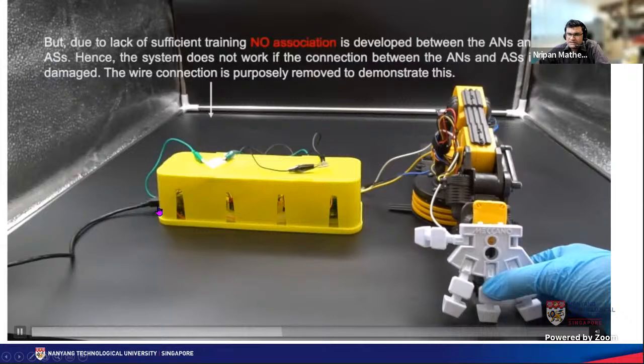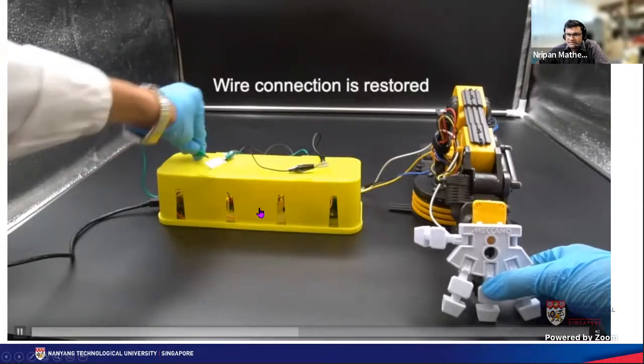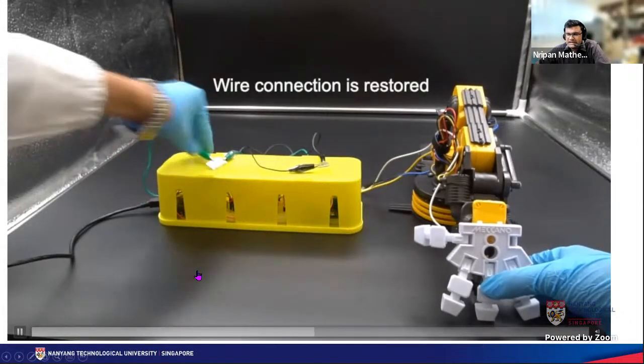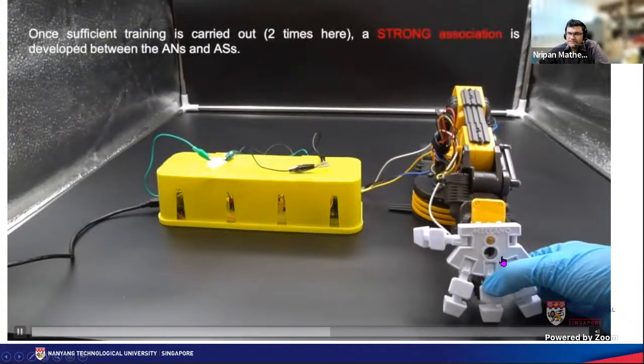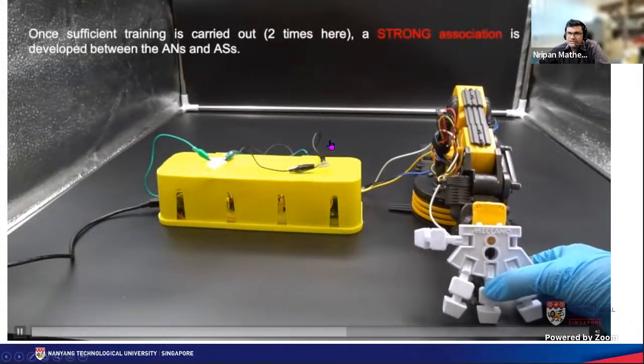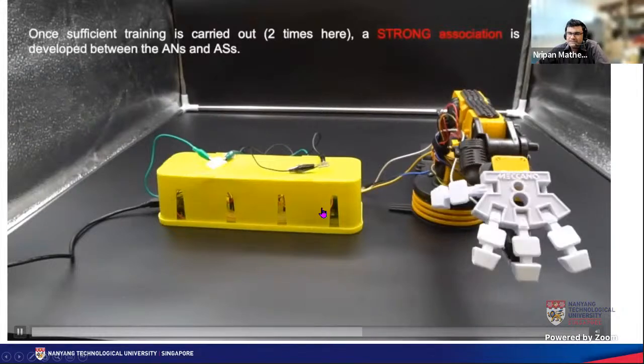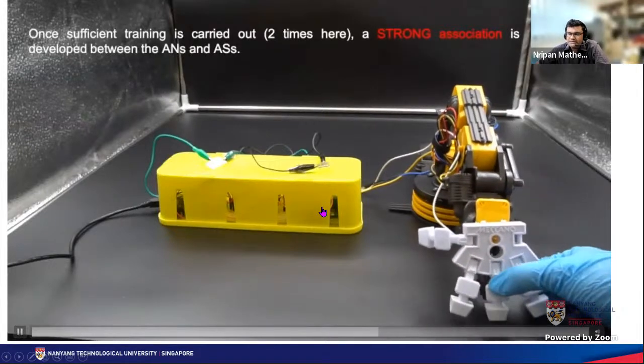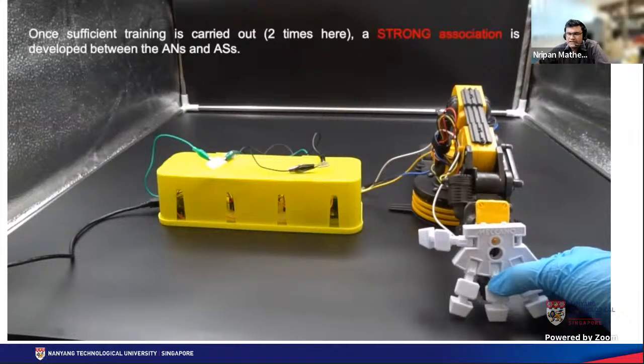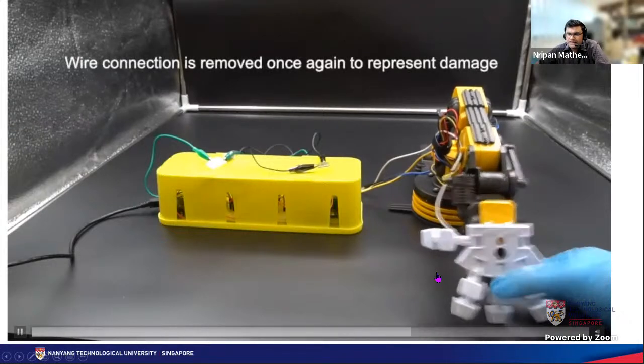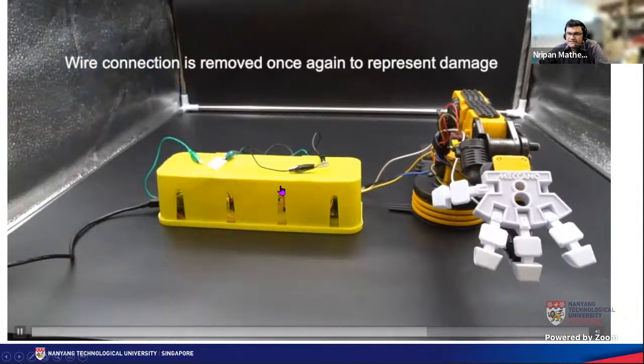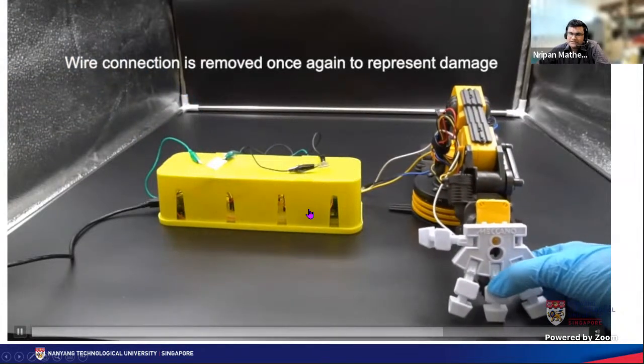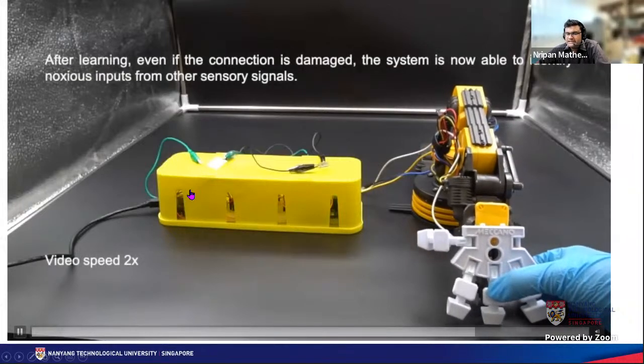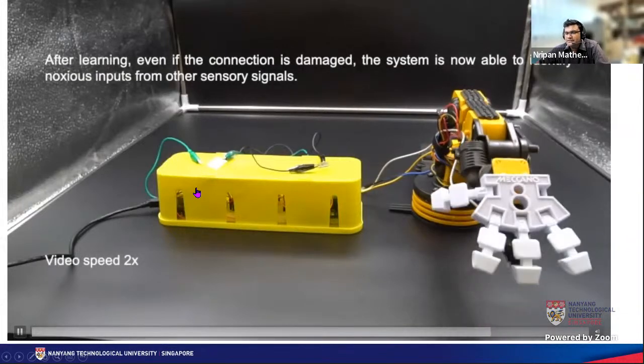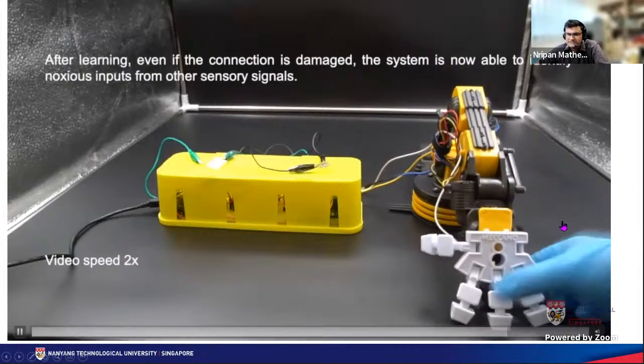But then we reconnected the nociceptor and the whole network connection, and then we trained it. So we pressed it roughly 2 times, and now we are making sure that the synapse programs or learns that the high pressure is a bad thing. So this is the training still occurring. The advantage of having this artificial synapse is that because you have local memory, even though now the system is disconnected, it still retains the memory that extremely high pressure is not good and it moves again.